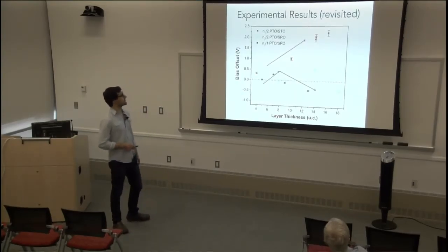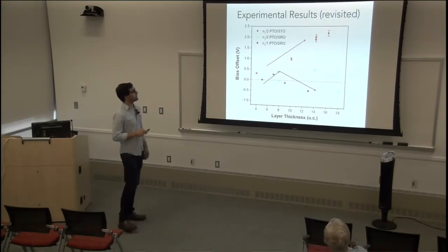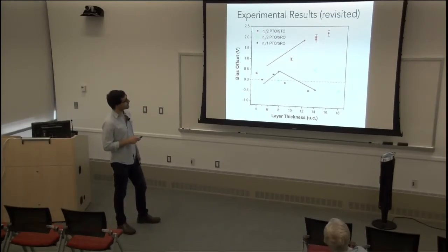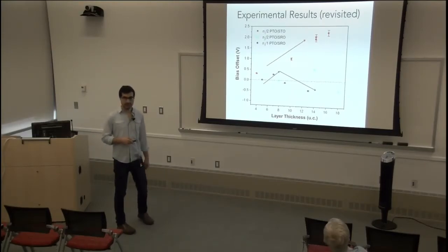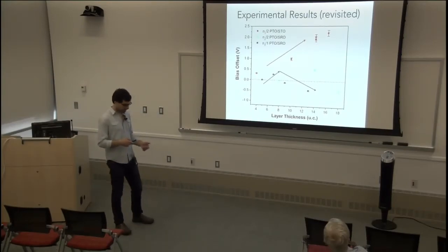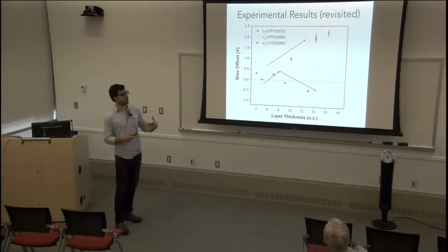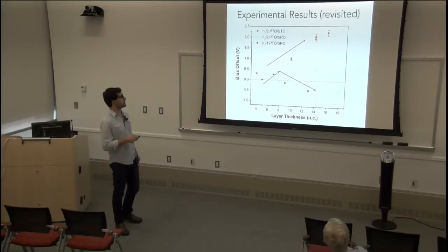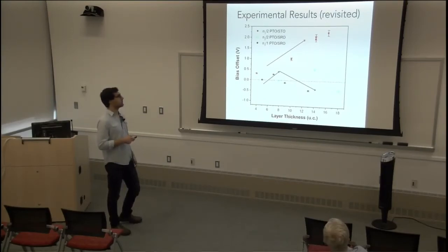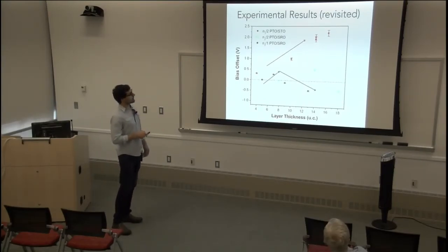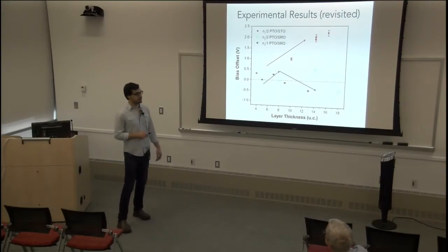So now to revisit the experimental results, we understand that in lead titanate, strontium titanate, this increase is due to the fact that you keep having more and more defects in your lead titanate, these oxygen vacancies. And these oxygen vacancies, remember, cause an asymmetric double wall, and this asymmetric double wall gives you a bias in the hysteresis, or the butterfly loop. In lead titanate, strontium ruthenate,